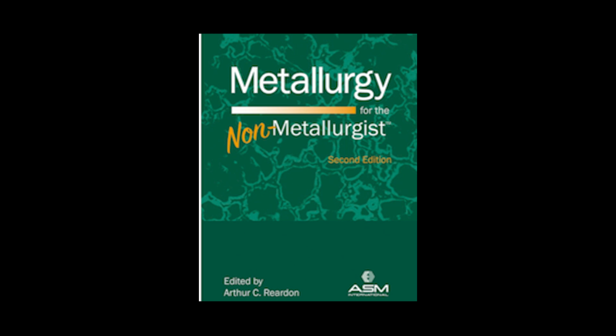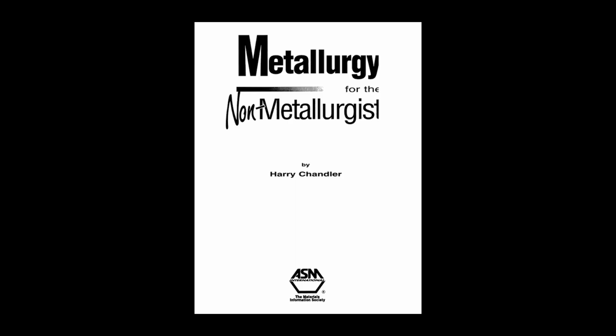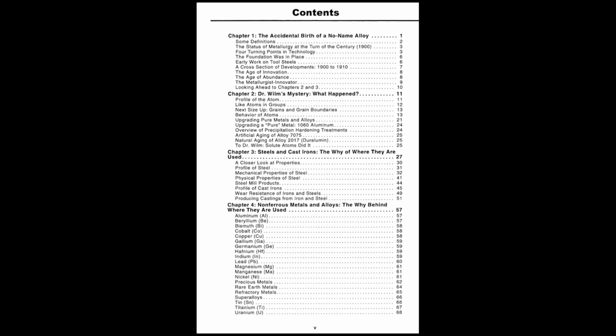What about common stuff like brass? Copper-zinc alloys. For brasses, annealing is a common heat treatment. Like with steel, it's used to soften the material, relieve stresses from cold working, and improve ductility so it can be formed more easily. And titanium. That's a high-tech material. Titanium alloys have their own complex heat treatments. Titanium can exist in different crystal structures, alpha and beta phases, depending on temperature and alloying elements. Heat treating allows metallurgists to control the amounts and arrangement of these phases to get specific combinations of strength, toughness, and fatigue resistance. Annealing is also used here.